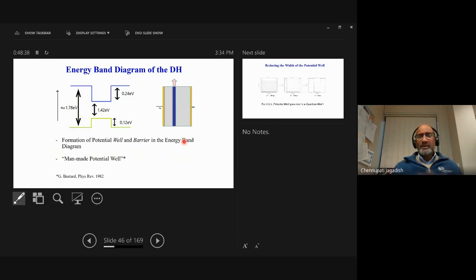So how does the quantum double heterostructure work, which we talked about? You have this smaller band gap material sandwiched between larger band gap material. This itself doesn't act like a quantum well unless you really bring the thickness of this gallium arsenide layer down to smaller thicknesses. Then it creates essentially a potential well, because electrons or holes which are here cannot go to the other side, as there's a barrier here. That's why it is called a man-made potential well by Gerard Bastard, as I talked about, creating this well and then the barrier.